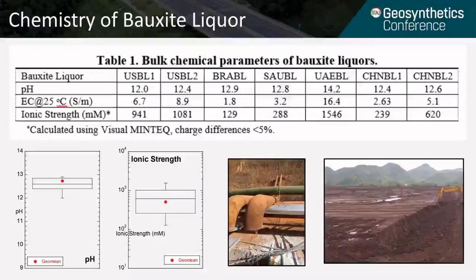We found that all these bauxite liquors are high in pH, all between 12 and 13, and some of them are close to 13. Also, the ionic strength is the measure of the total concentration of ions in the bauxite liquor, so higher means you have more dissolved phases in the liquor. In this case, the geometric mean of the ionic strength is around 500 to 600 millimolar, while some of the bauxite liquors can be as strong as 1.5 molar.